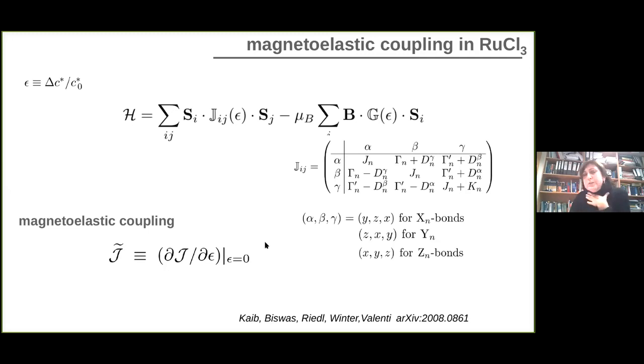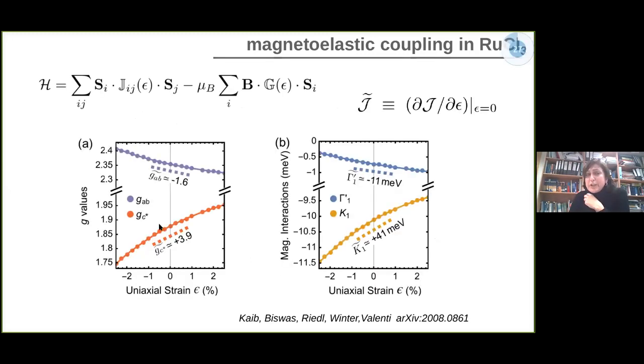And now what I wanted to go to is calculate the magnetoelastic coupling in the system by making use precisely of the fact that we have all these uniaxial strain dependent interactions, so we can obtain the corresponding magnetoelastic couplings for each one of these interactions by calculating the slopes of these curves.